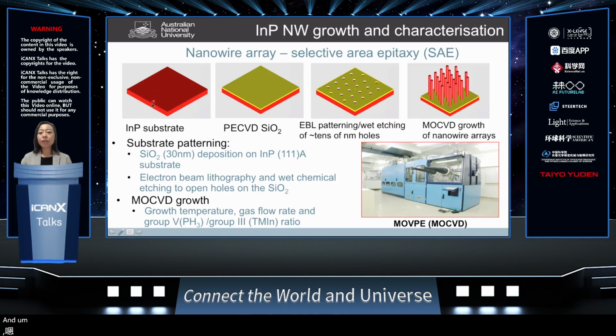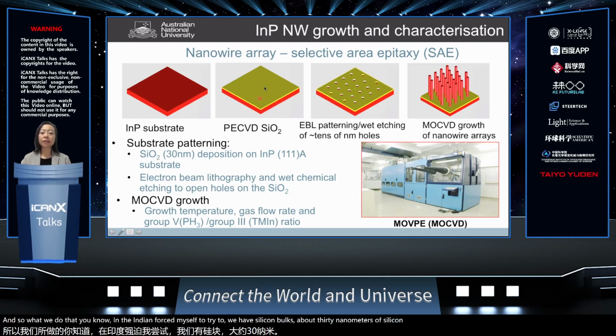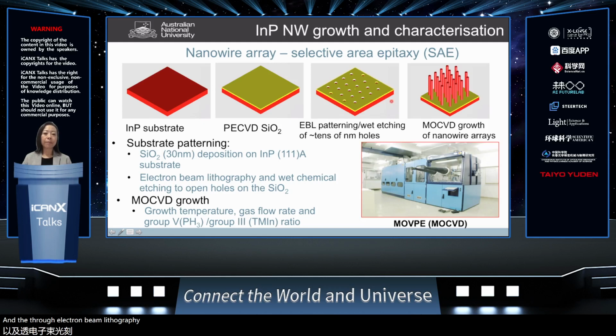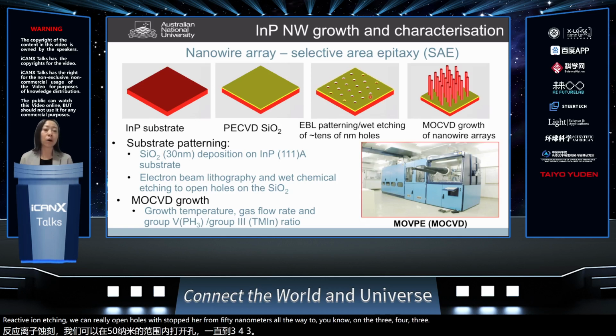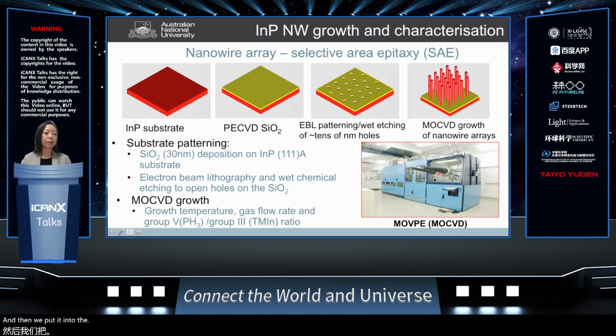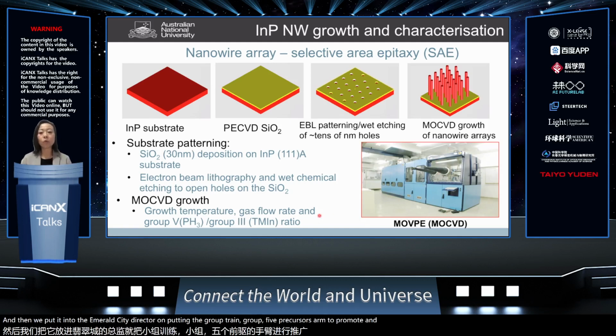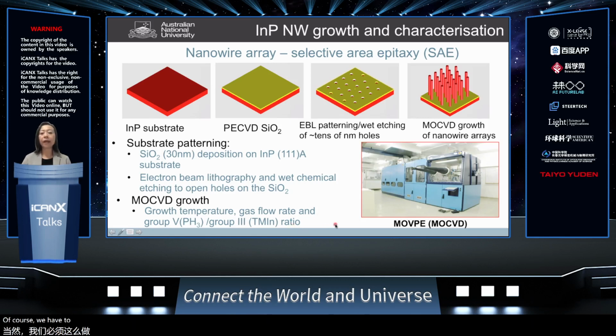And so what we do is that, on the indium phosphide substrate, we deposit about 30 nanometers of silicon dioxide. And then through electron beam lithography, combined with wet chemical etching or RIE, reactive ion etching, we can open holes with diameters from 50 nanometers all the way to 300 or 400 nanometers. And then we put it into the MOCVD reactor, putting in the group III and group V precursors to promote the nanowire growth. Of course, we have to really understand the growth and control the growth temperature, gas flow rate, and also the pressure in the system.